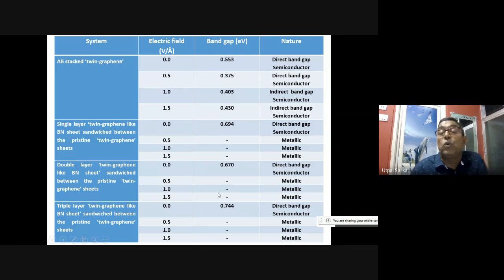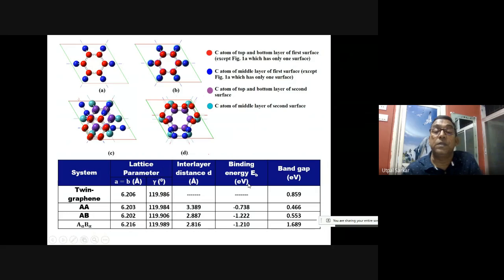So depending upon your electric field and material, it is not only changing the position of the band gap, the nature of the band gap, and the value of the band gap, it is also changing from semiconducting to metallic property. That you can tune. So this is a very good, interesting thing.